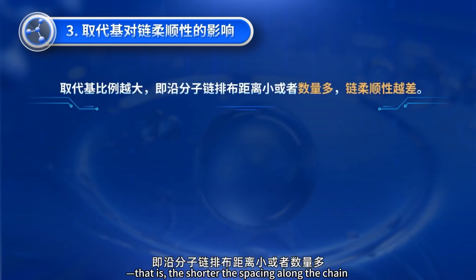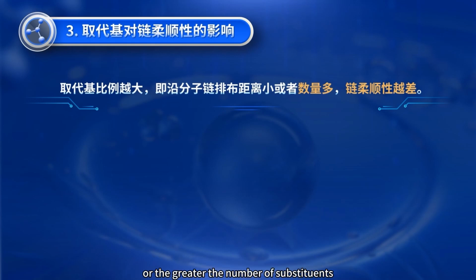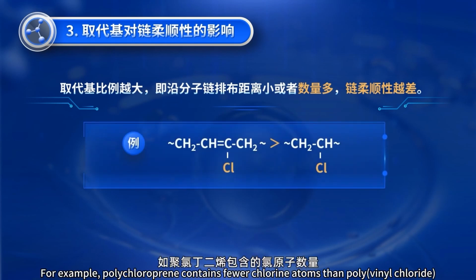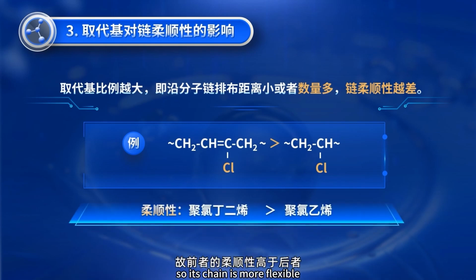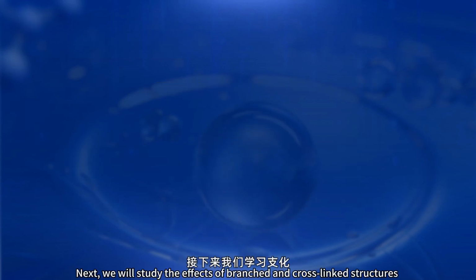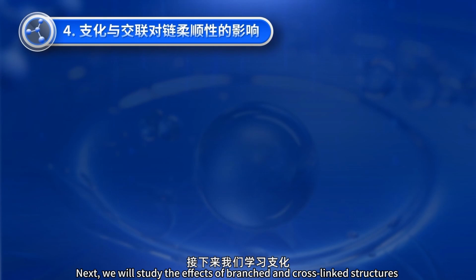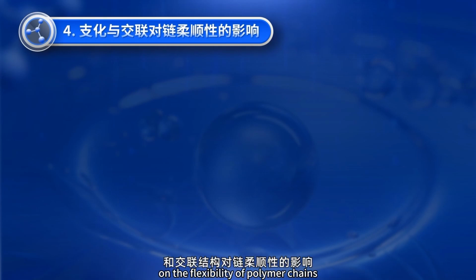that is, the shorter the spacing along the chain or the greater the number of substituents, the lower the chain flexibility. For example, polychloroprene contains fewer chlorine atoms than polyvinyl chloride, so its chain is more flexible. Next, we will study the effects of branched and cross-linked structures on the flexibility of polymer chains.